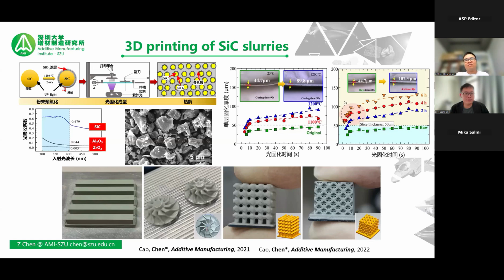printability. Then you can see from the left hand side the single layer thickness can be improved like 3 times. So it's now like 107 micron, and the original one is 40 micron, so it's 3 times. And now we have like 120. So afterwards, based on this strategy, we can successfully produce 3D printed silicon carbide material with highly complex structures. And you can see that we can apply the whole strategy very smoothly to different kinds of structures. And you can see that after printing, after sintering, the structure is very delicate and we can obtain very refined structures. And the next one is photopolymerization for the